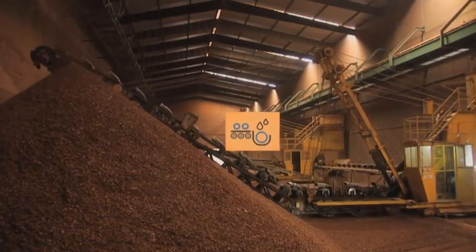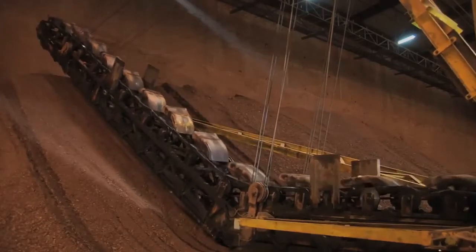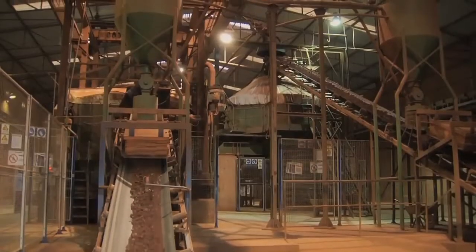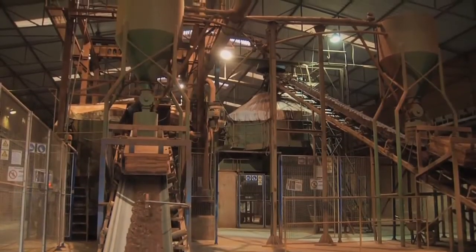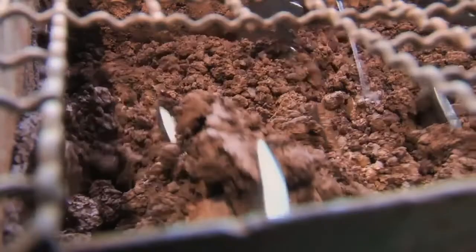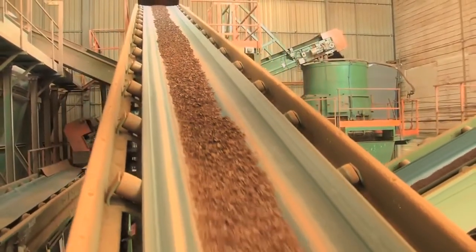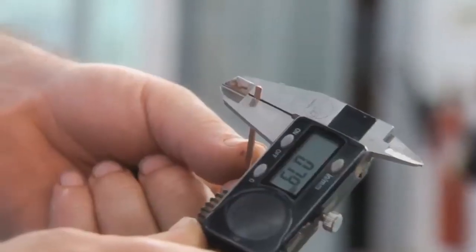The preparation of the clay is a vital stage in the production of tiles. Hoppers are used to transport the clay to crushers, wet pan mills and roller mills, which reduce the size of the particles by means of friction and crushing. After it has been stored in an interior silo, the refining process takes place, during which the mixture is kneaded and humidified, and then roller milled once again. At this point, the paste acquires its final consistency.